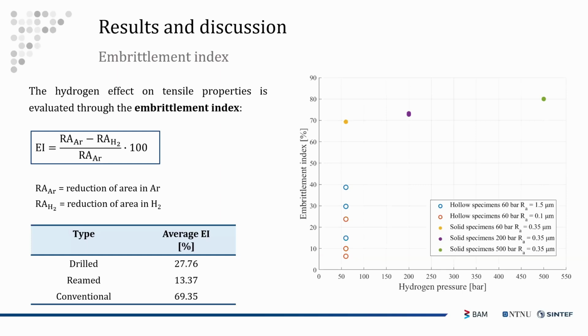And we can see that even if the embrittlement index obtained with the drilled and reamed specimen and conventional specimen is basically not comparable, because the geometry of the specimen is way different, we can see that the higher the pressure of hydrogen in the autoclave, the higher will be the embrittlement index. So we don't see any saturation effect up to 500 bars. And this is quite interesting, because increasing the pressure of hydrogen within the pipe, we will also increase the susceptibility of the steel. So we have a continuous degradation as we increase the pressure.